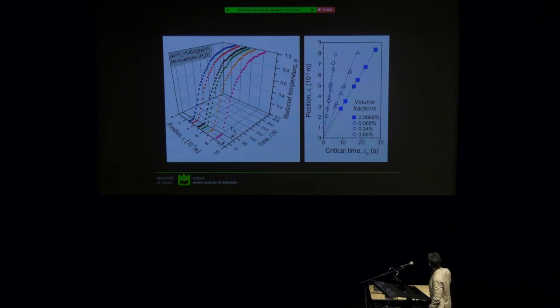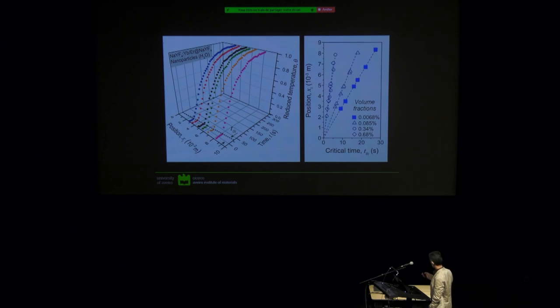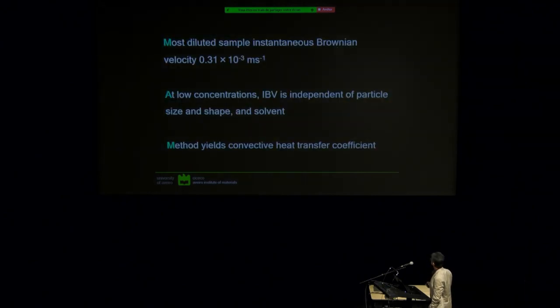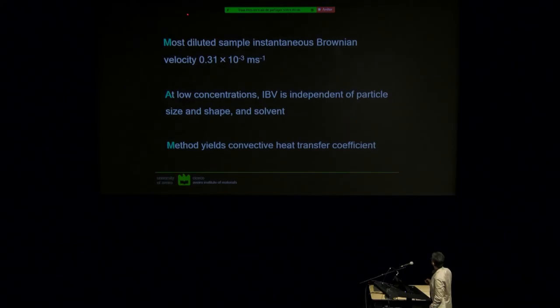And so we had this delay before temperature starts to increase, which we call critical time, and this can then be plotted against the position, and we consider different volume fractions, so more or fewer crystals in the water, and we got straight lines. It's interesting that for diluted samples, we have a velocity which is very, very close or equal within experimental error to the instantaneous Brownian velocity. And that's the value. All the paper is showing that this is indeed instantaneous Brownian velocity and not something else. And we also showed that at least at low concentrations, this instantaneous Brownian velocity is independent of particle size and shape and solvent. So we produced nanoparticles with cylindrical shapes, for example, and so on.